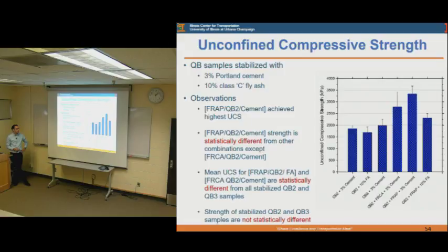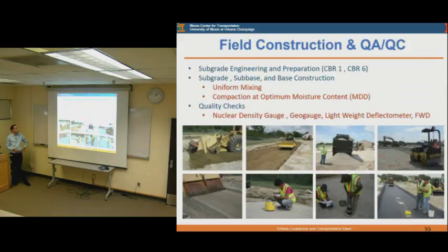Some of the strengths are more statistically different than others. For example, these two sections are statistically different than when we only have the quarry byproduct stabilized with either cement or fly ash without any other recycled material, RAP or RCA. So for the field construction, QA and QC, it was similar procedures. So we had the density measured, we had the LWD and the GeoGauge deflections and modulus, so deflections and then back calculating the modulus, as well as the FWD. And we also engineered the subgrade in a similar manner as I was explaining for cell 1.